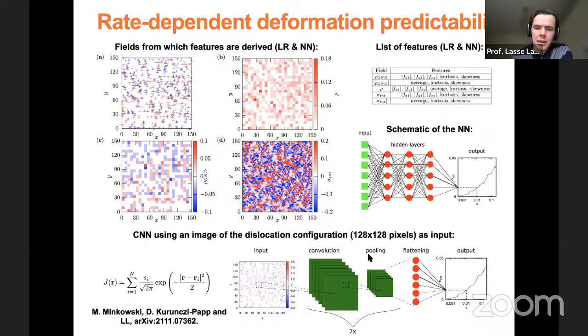Then we also have the CNN, where we use as input an image of the initial dislocation configuration, which looks like this. So actually what we do is we first represent each dislocation with a Gaussian function to make this descriptor independent of the resolution to some extent, because these are point particles. So of course we don't want to describe them as mathematical points, but rather as some kind of more diffuse object. And then we choose a resolution for this field here, which is in this case 128